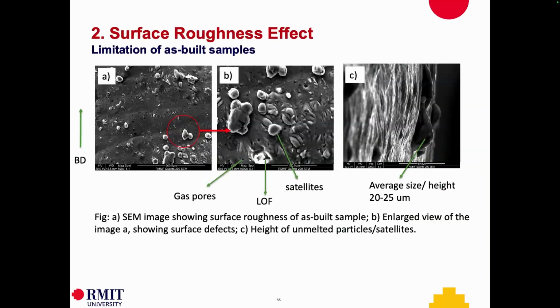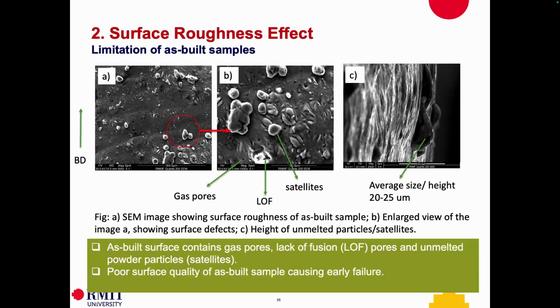Then we look at what is going on in terms of different pores. As I said, we normally get gas pores, which are spherical, lack of fusion pores, which are kind of irregular shape. And the average height of these satellites is about, we found 25 micron, which is an issue here because 25 micron is kind of the initial crack length we find in aerospace metals, which is similar to the height of this satellite, which is unmelted particles within these AM structures.